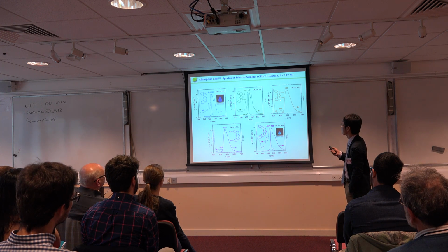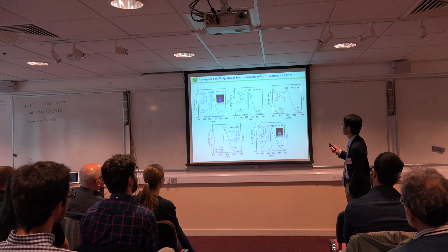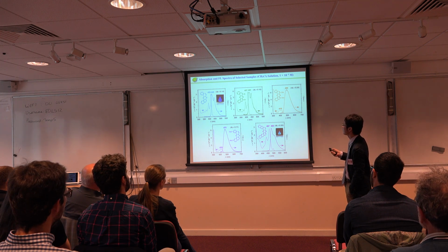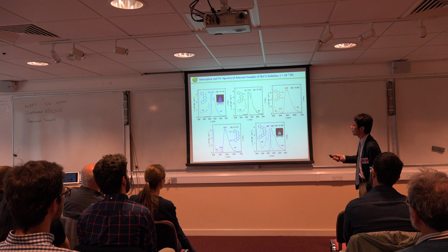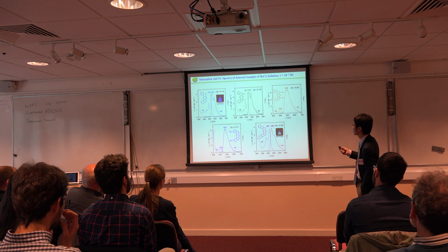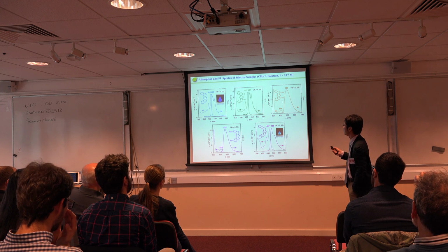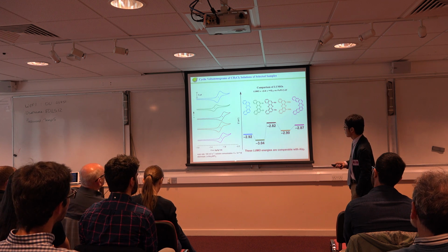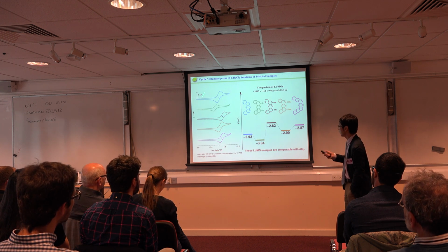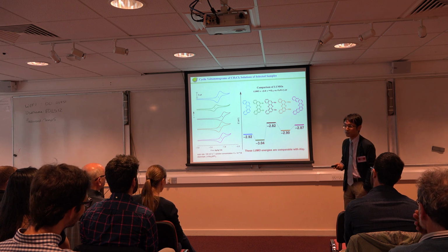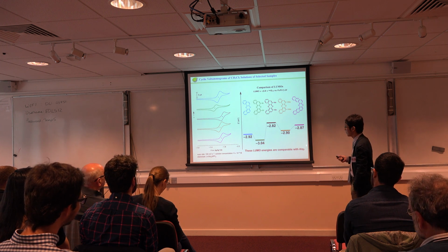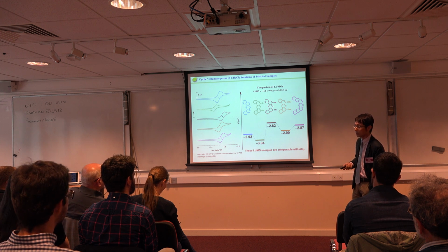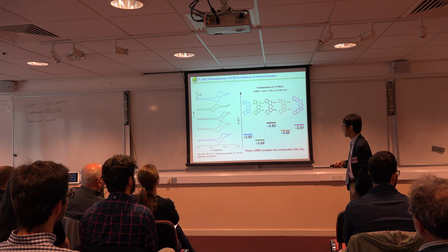Especially when you put donor units in the highly conjugated systems, the emission properties can be changed from the locally excited type to the charge transfer type, shown like this. They also have good electron accepting abilities, like Alq3, so they can be utilized as electron accepting or transporting materials in devices.